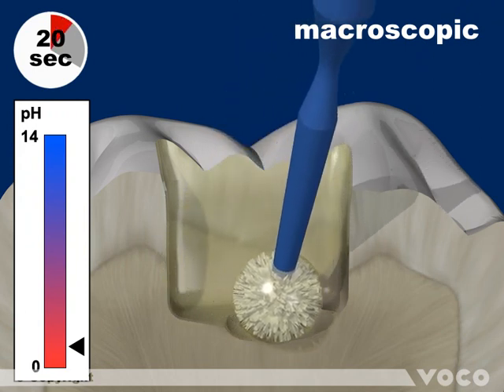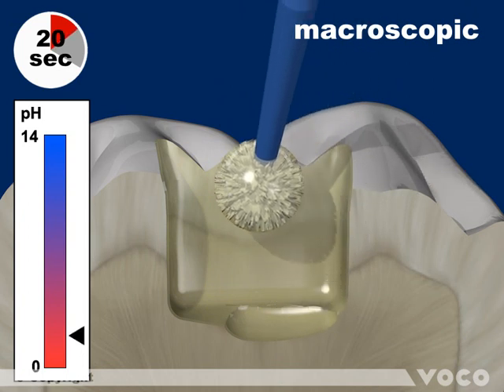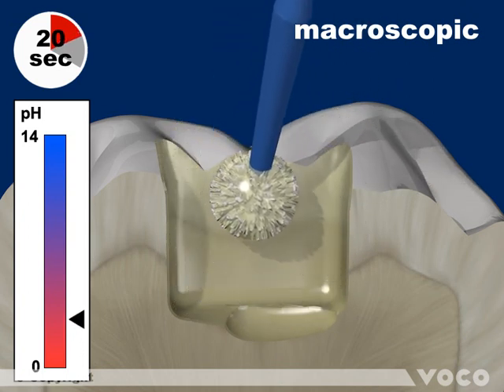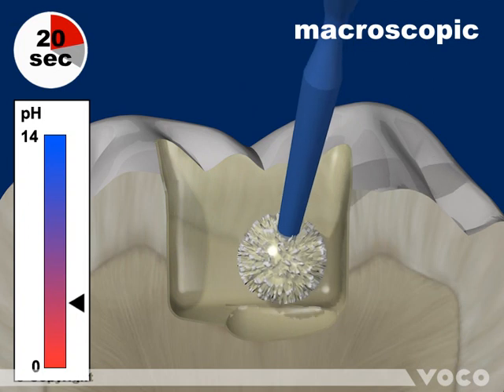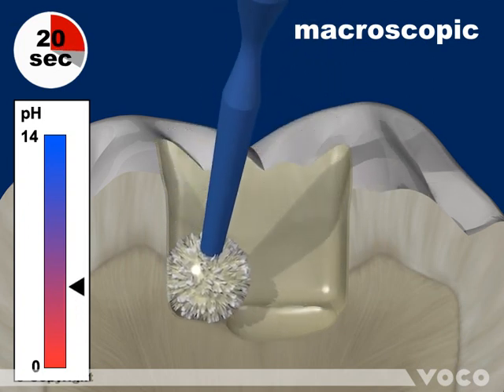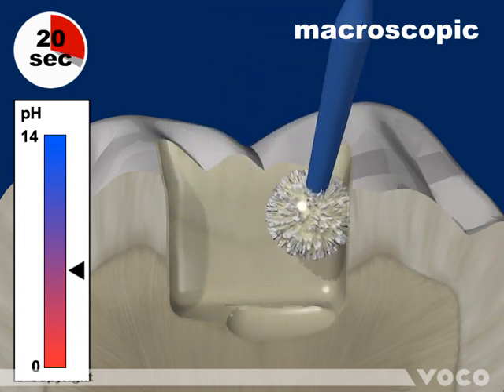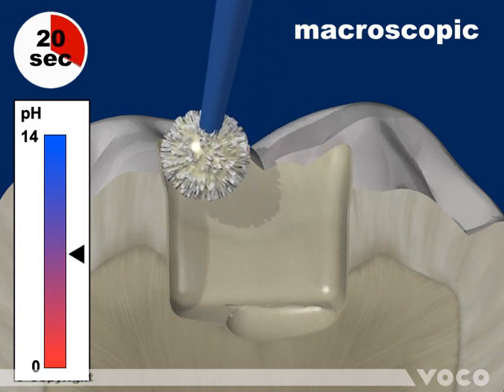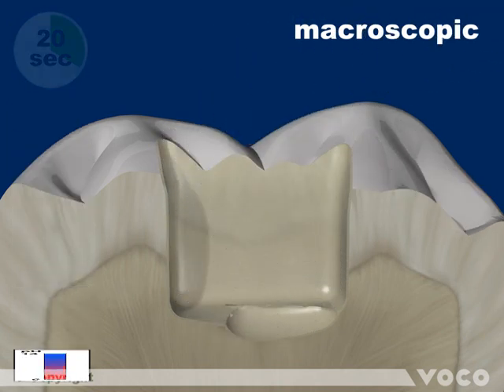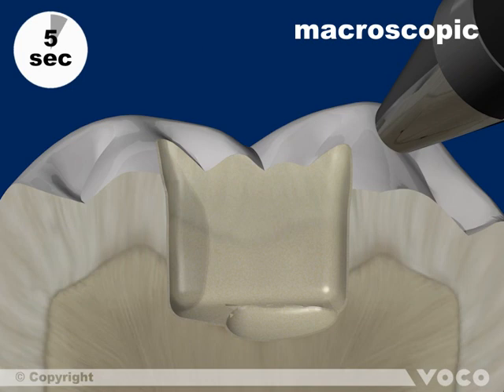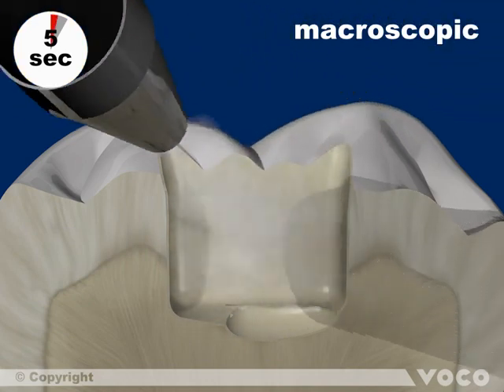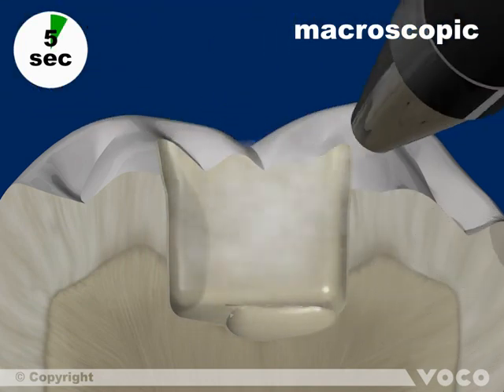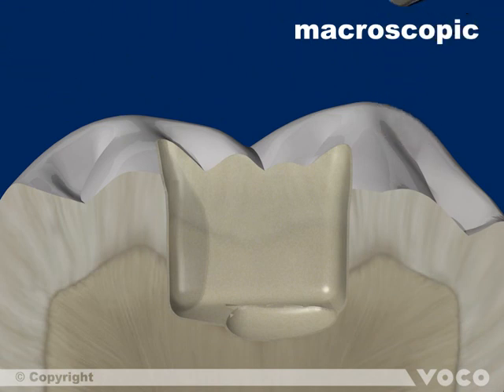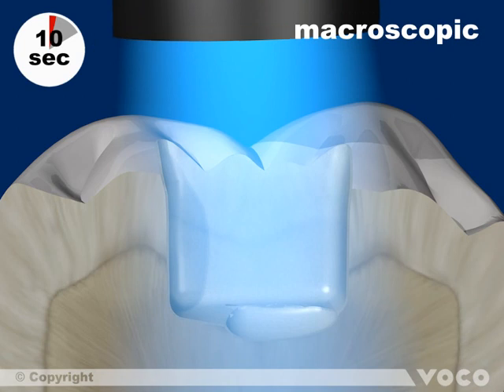The initial acidic pH value rises during this process to a neutral level. Gently air drying, thus evaporating the solvents from the adhesive. Light curing of the adhesive layer for 10 seconds with a minimum of 500 mW per square centimeter.